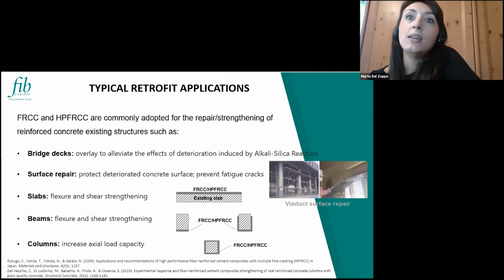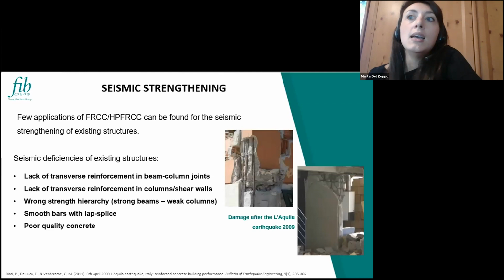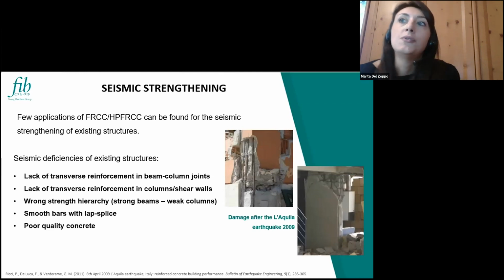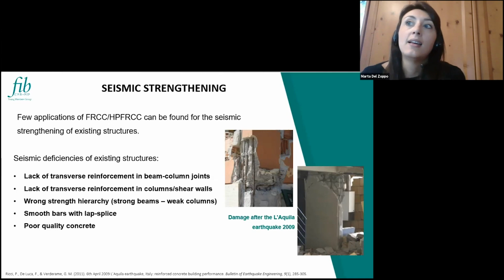In the case of the beams, we can increase both flexure and shear capacity thanks to the application at the bottom of the beams or on three sides, like a U-wrap of the beam, with this additional fiber reinforced cement composite jacket. Or in the case of columns, adopting a full jacketing of the member with this new material, we can increase the axial load capacity thanks to the confinement. The adoption of such materials for seismic strengthening is still under investigation, and only a few examples can be found up to date in literature.